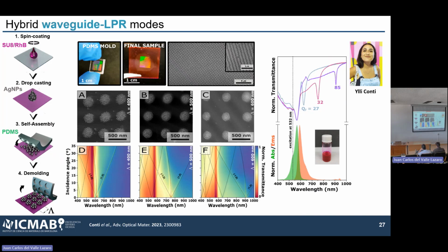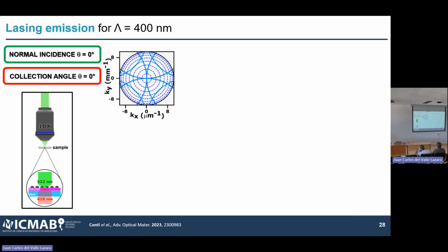And so as you can see here, again, the values are pretty high for a colloidal system. Of course, there are higher ones in the literature, but these start to be nice resonances from a photonic standpoint. And so we decided to see how we can modify the emission properties of rhodamine B using this strategy. And so the idea was to create a lasing architecture.